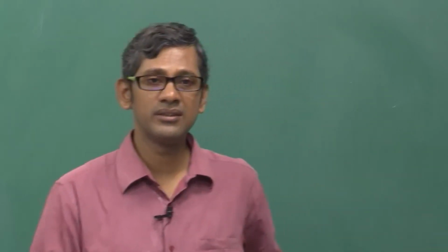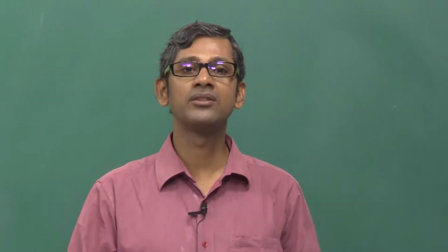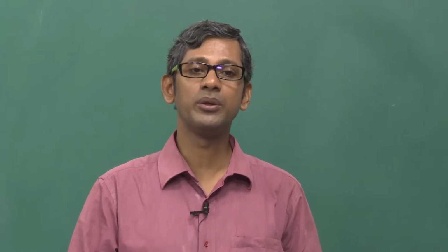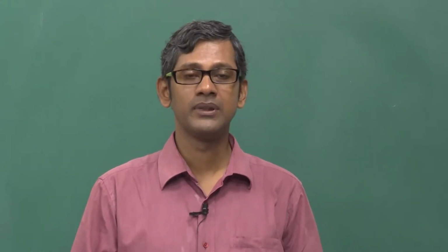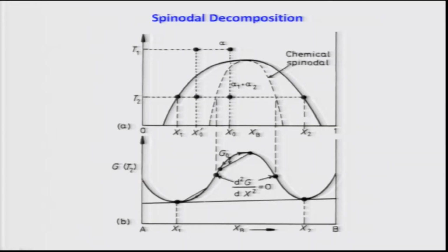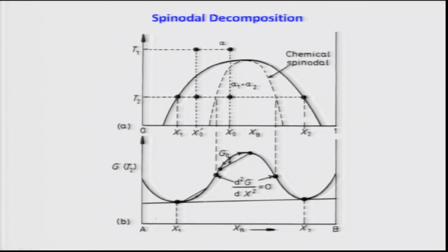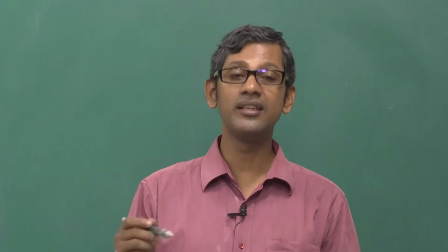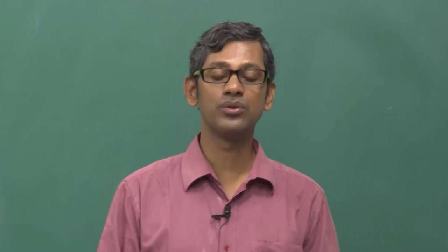and the one which is very distinct and different from the normal solid solutions is the one in which the free energy versus composition diagram shows a hump, just like a road bumper. So you can clearly see that free energy initially was like this, then it decreases, passes through a minimum, again increases, reaches a maximum value, decreases, again increases. So as you go from pure A to pure B, only at both the ends the free energy is decreasing initially as the composition of the solute increases. As the composition of B increases, the free energy is decreasing, but then there is a composition beyond which it starts increasing and reaches a maximum value. That is why I say it shows a hump.